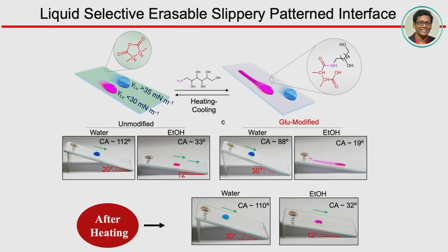So with that particular understanding, we thought, okay, our interface is chemically reactive in nature. Now let's go for the post modification and see its behavior. So initially you started with an interface which is omniphobic in nature. Okay, it slides ethanol, water, and all different kinds of liquids. But when you modify with glucamine, then it compromises the sliding behavior against only the low surface tension liquid, where the liquid surface tension is less than 30. Okay, and you can see this is the unmodified, and then after glucamine modification it is compromised. But once you heat it up, this interface again regains its property.